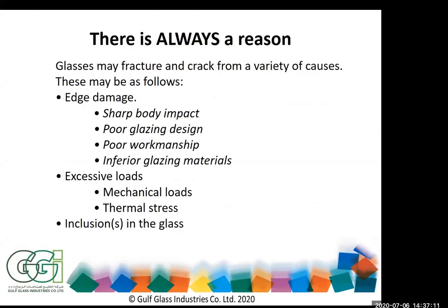Glass may fracture and crack from a variety of causes. They may be edge damage, which can be caused by sharp body impact, poor glazing design, poor workmanship, or inferior glazing materials. Other reasons for breakages are excessive load, mechanical loads, and thermal stress. Last but not least is inclusion in the glass. There's always a reason for glass breakage. Sometimes it is easily diagnosed by looking at it, but sometimes it needs experience and expert opinion to look at it and analyze it.